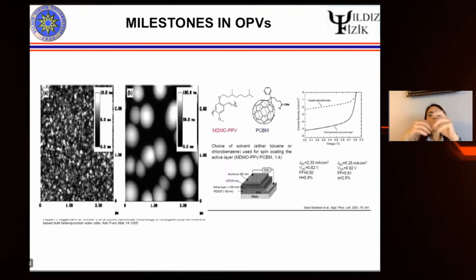And they were mixing or blending them in toluene as a solvent, and they were casting the active layer on top of this PEDOT:PSS layer. Later on, people realized that instead of using toluene, what happens if we use chlorobenzene? Because as physicists, when we look from outside, they're all clear solvents, and for me it is very difficult to distinguish which one is which.